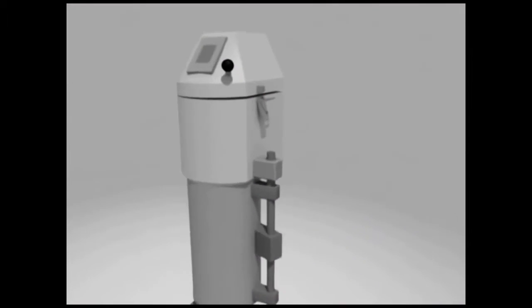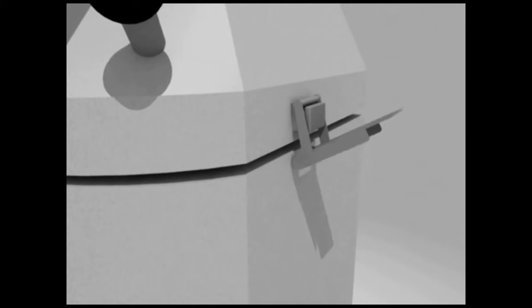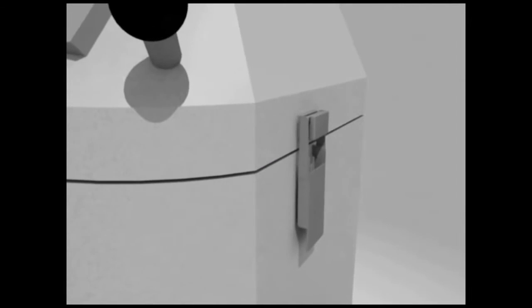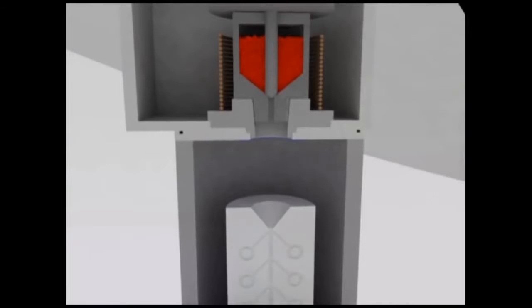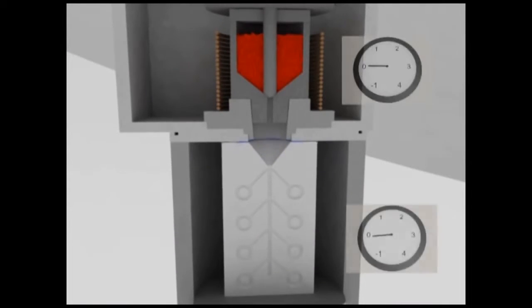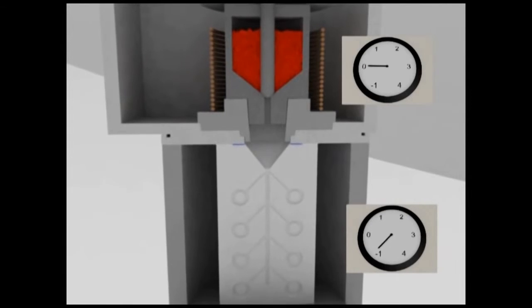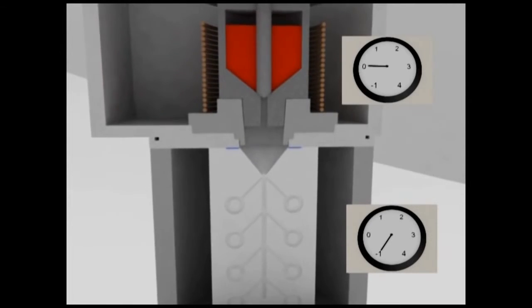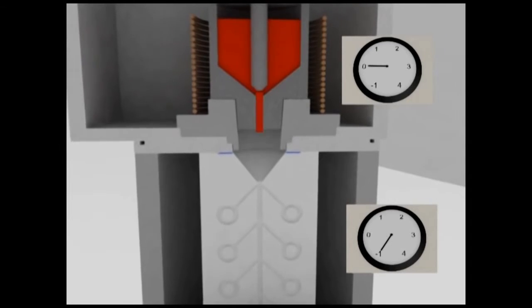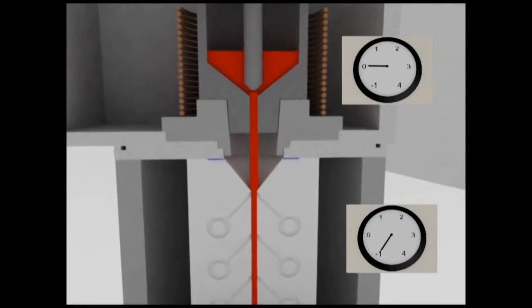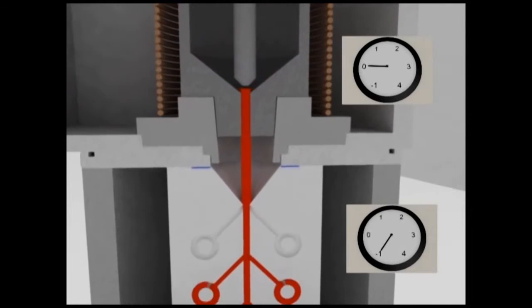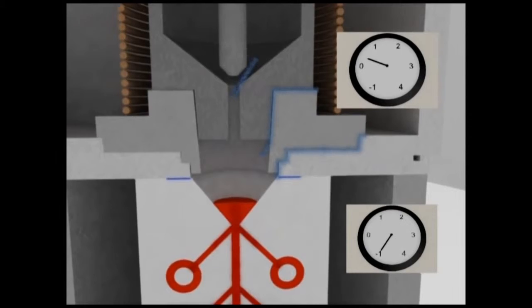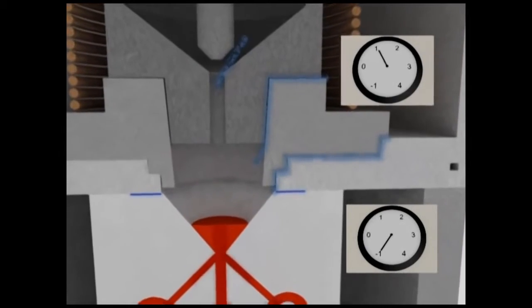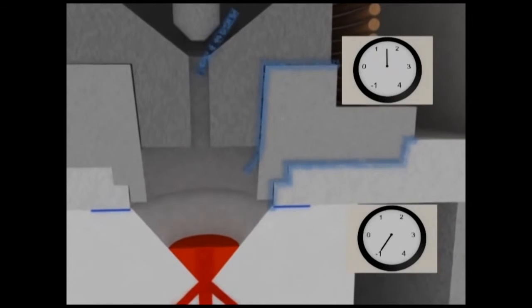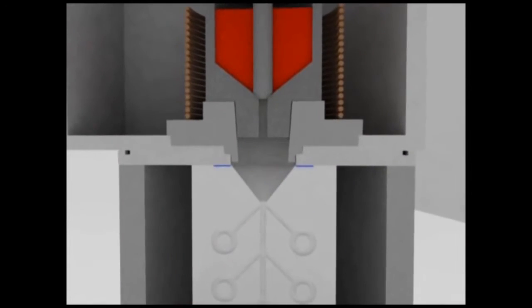In most of our competitors' machines, the metal cannot be effectively pressurized up to 4 bars, since the machine's structure does not allow for this, and under this pressure the cover will blow out. During normal use at 1, maximum 2 bars, the applied gas pressure above the crucible can only act on the metal once the mold is occupied, by jetting through the crucible feed hole to the underside. The effect of this pressure is drastically reduced by drag of the crucible holder, etc. In fact, application of gas overpressure by this method shows no significant advantage over a simple gravity vacuum system.